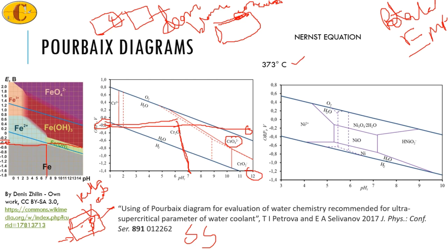If you have chromate formation, it means that the chromium oxide film has reacted with the oxygen and it is actually lost. So you don't have the intact chromium oxide film, you'll have some kind of a porous film from the top. If you have a porous film, then the NaOH, or the caustic environment, is able to react with the Fe to form FeOH underneath, and that will lead to corrosion of the stainless steel.